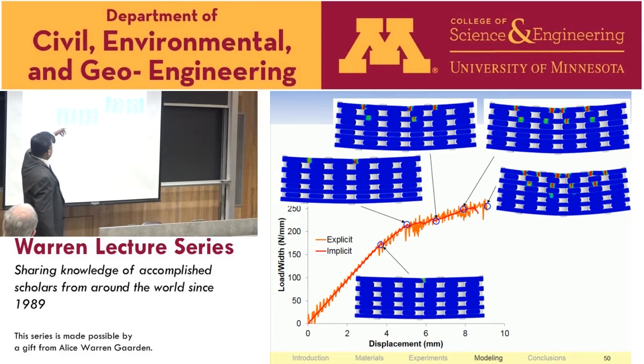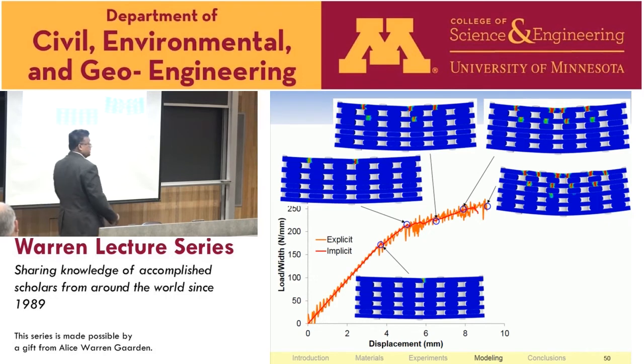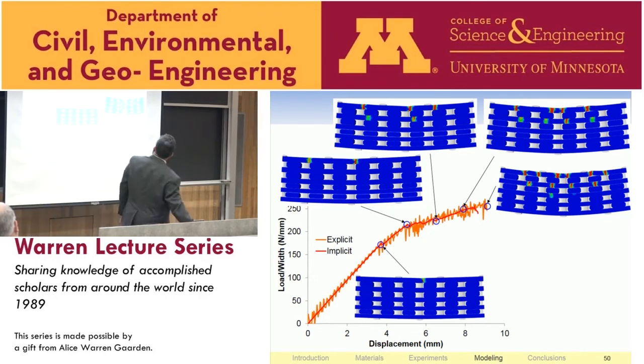Now, while this is going on, I removed the matrix. The matrix is cracking at the bottom, the matrix elements. I removed it to show, because the tows actually control the global collapse, but the progression of failure in the tows is controlled by the matrix. So it's a progressive failure with interaction between the constituents.